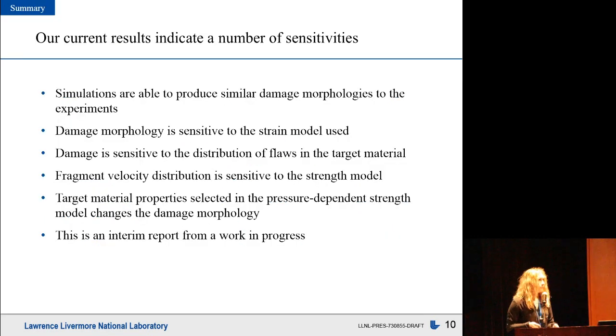So in summary, we are encouraged by our current results, which indicate a number of sensitivities. We find through the scans we've done so far that the simulations are able to produce similar damage morphologies to the experiments. Damage morphology is sensitive to the strain model used, and sensitive to the distribution of flaws in the target material. Fragment velocity distribution is sensitive to the strength model, and target material property selected in the pressure-dependent strength model changes the damage morphology in the target.